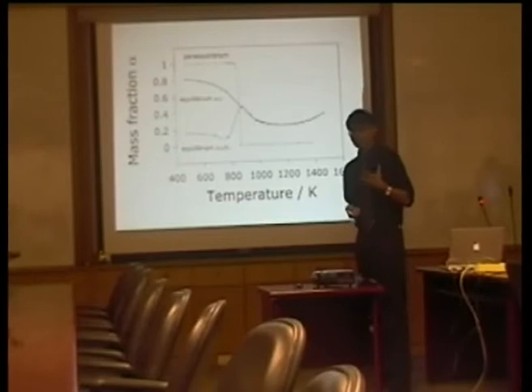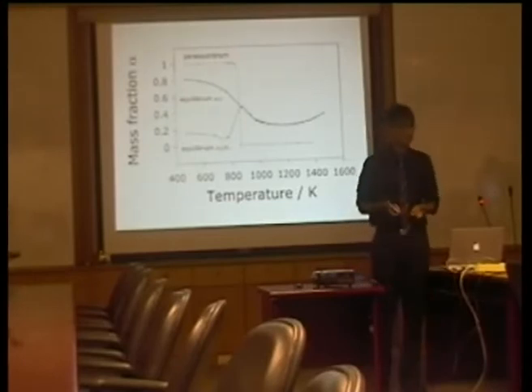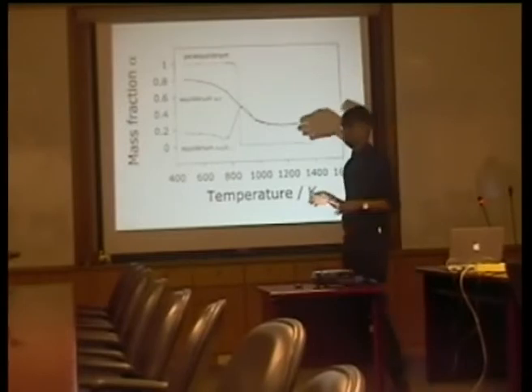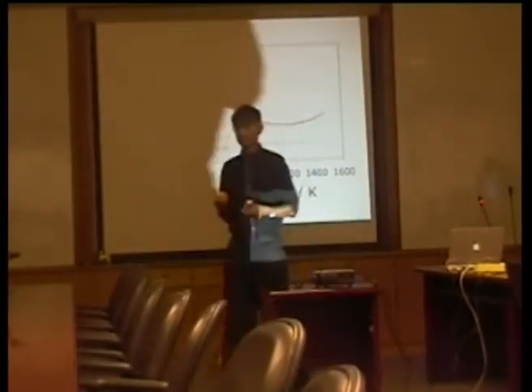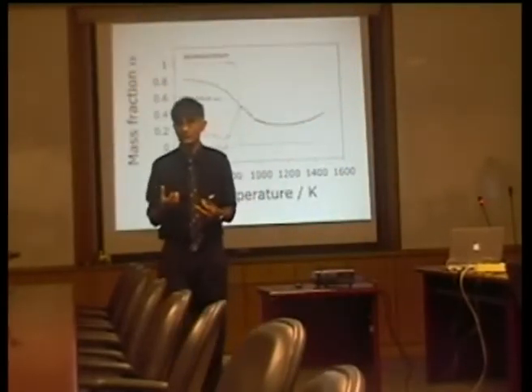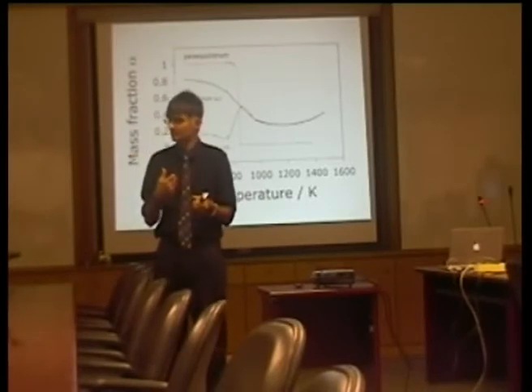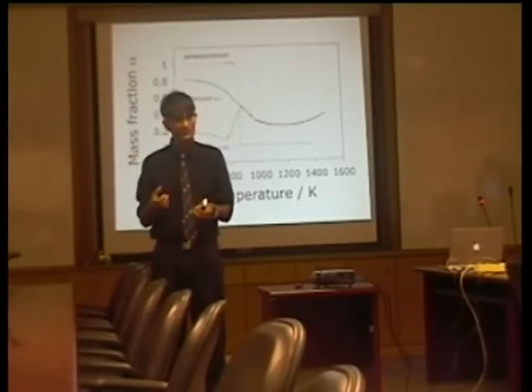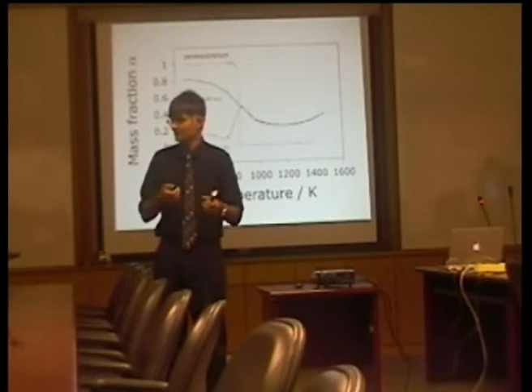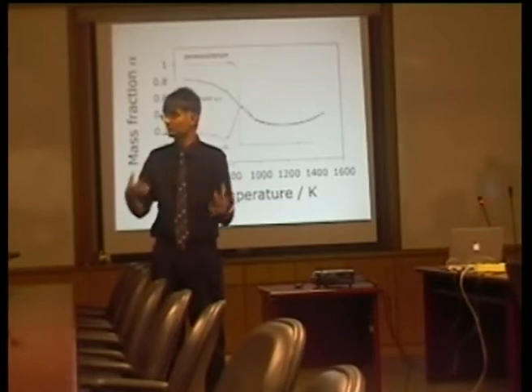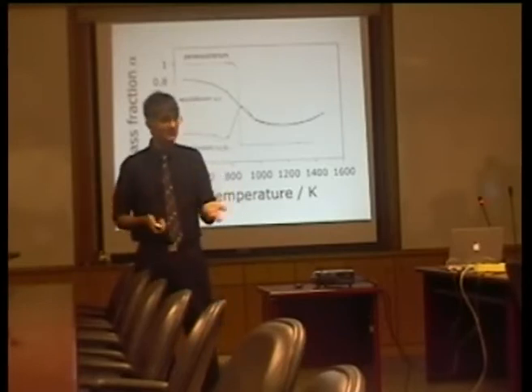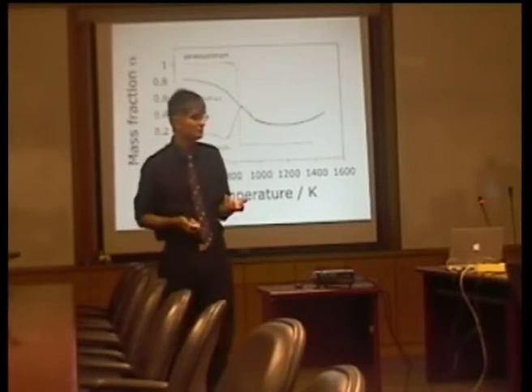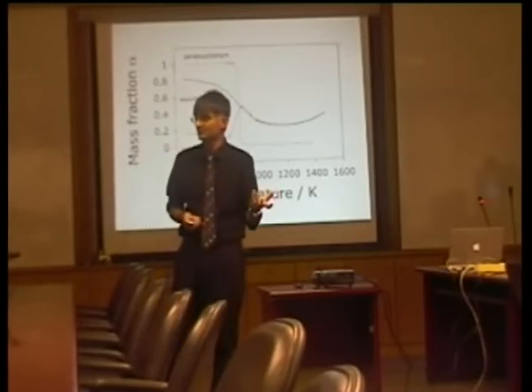If we do an equilibrium phase diagram calculation for 316L, equilibrium means the ferrite will have the composition that it wants to have, that means it will reject nickel. The austenite will have the composition it likes, that means it will reject chromium and become rich in nickel. And we might even have carbide precipitation, for example, M23C6, chromium carbide or cementite, etc.